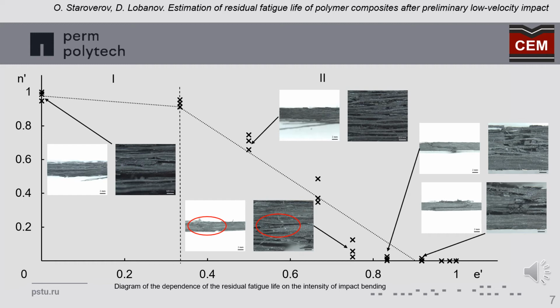In the case of fatigue failure without preliminary impact, the carbon fiber reinforced plastic specimen delaminated through the entire working area. Broken threads and multiple delaminations are visible on the fractures. Similar fracture patterns were observed for fatigue after impact with an intensity ranging from 0.33 to 0.66.